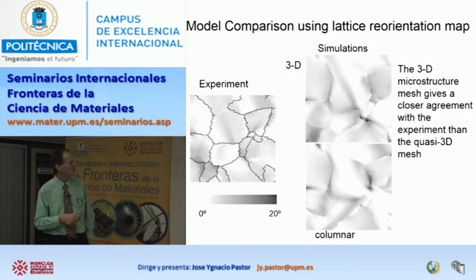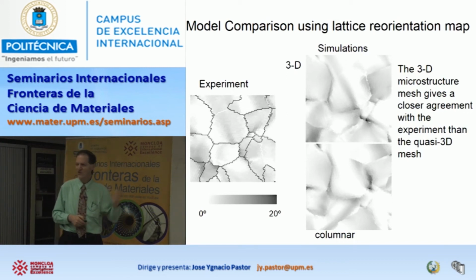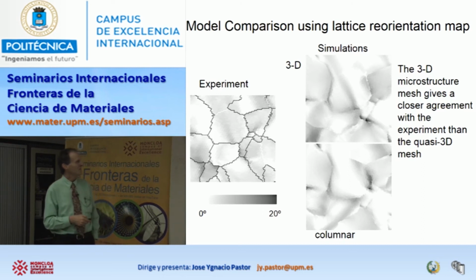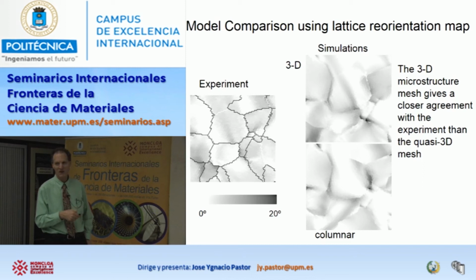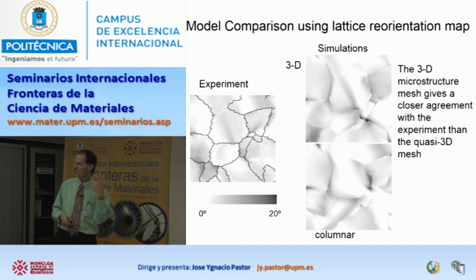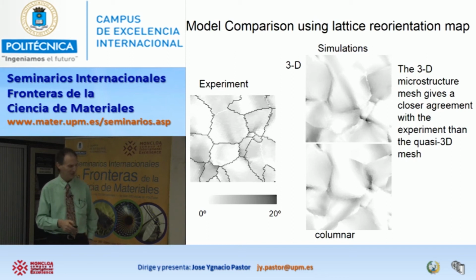And then if we compare a measurement of how the orientation changed from the starting condition to later, we see that there's maybe about a 10-degree change in a band right through the middle of this grain. And the simulation that we did with the 3D microstructure picked that up. But in the case where you just used the columnar microstructure, it didn't. So that means the true shape of the grains really matters when we want to simulate a microstructure. So the 3D shapes are important. Otherwise, we get something that doesn't match with what we actually measure.